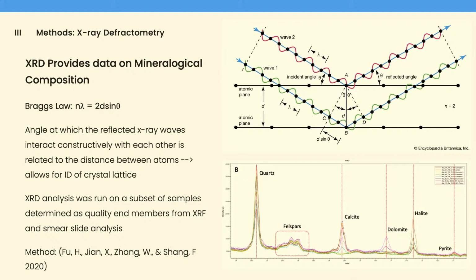XRD analysis was run on a subset of 16 samples, and I determined which samples to utilize based on smear slide and XRF data. I chose some end members that I felt like would represent the mineralogical composition of the sediments fairly well, and that were localized around particular areas of interest.